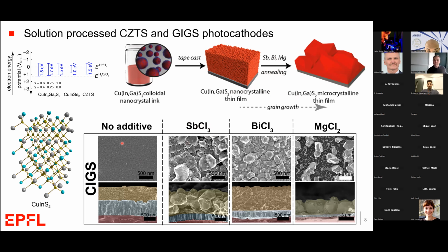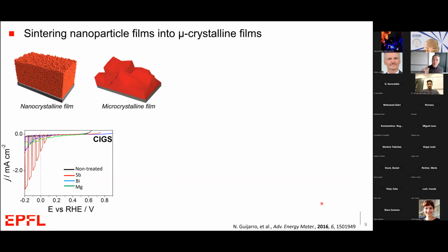So these SEM images give some indication of the effectiveness of adding these additives. Without any additive, you can see the cross-sectional SEM image of our device. Here's the substrate, and then here's the nanoparticle film. But at the same temperature, with these additives, you can see a large growth of the crystal grains. This creates a huge difference in the photocurrent that we get for the hydrogen production reaction.